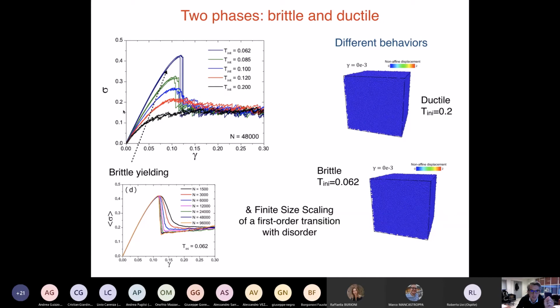And what you see is that here, in the sigma versus gamma, for the not well annealed system, you find a curve which is this. All these different curves correspond to different samples. So you have fluctuation, but you find something which has no overshoot, no discontinuous behavior besides the small fluctuation that will disappear in the thermodynamic limit anyway. Instead, when the system is very well annealed, you find that the sigma increases, but then has a very discontinuous jump, and then you have the plastic behavior.